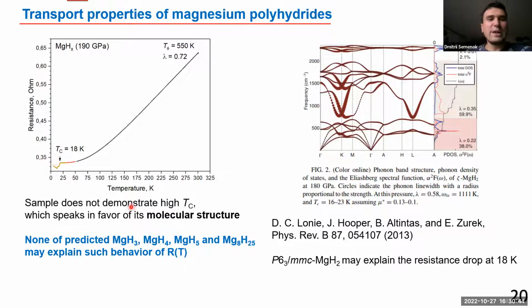So it means that probably all of the hydrides I discussed, magnesium H3, magnesium H5, and higher hydrides, all have a molecular structure. They are not atomic. That's why they do not demonstrate any pronounced superconducting properties. We do not see any deviation from the Bloch-Grüneisen curvature or equation in this dependence of electrical resistance on temperature here. Maybe this partial drop corresponds to superconductivity in magnesium H2, maybe.